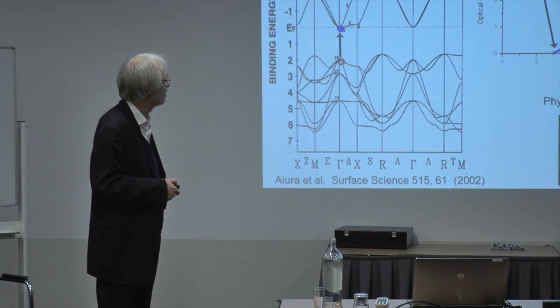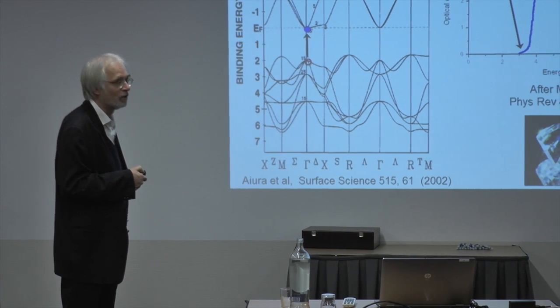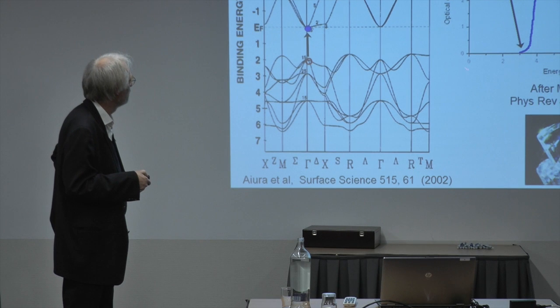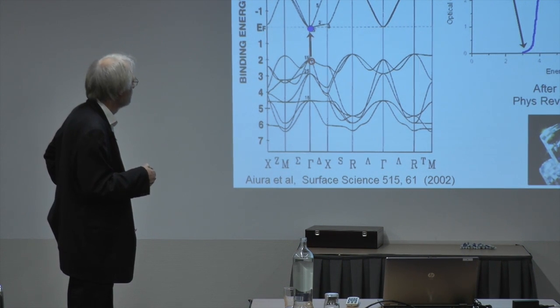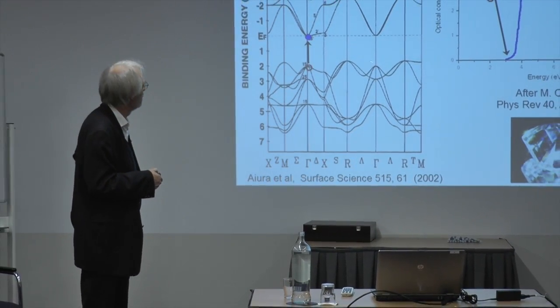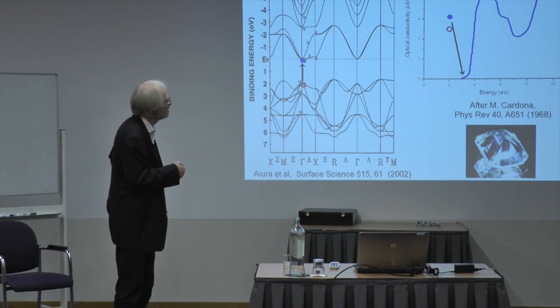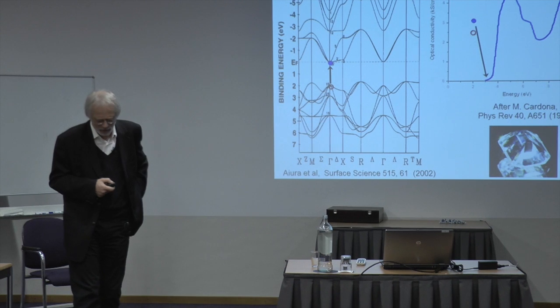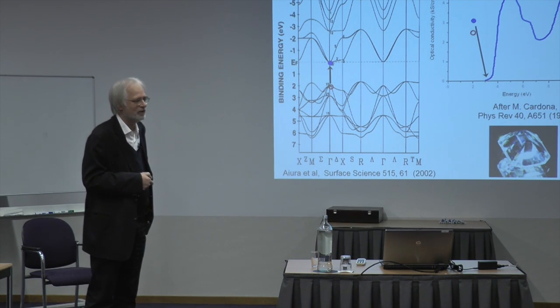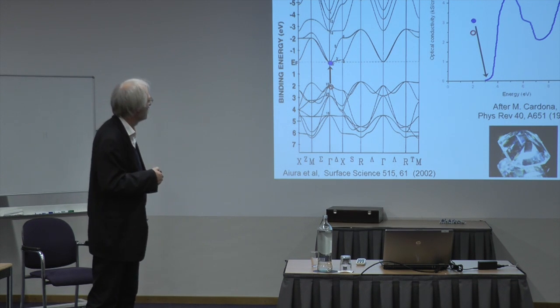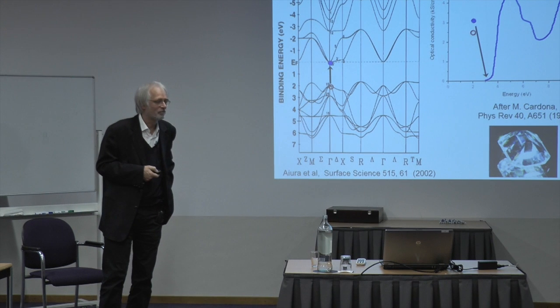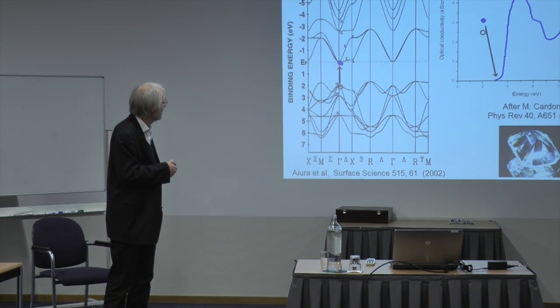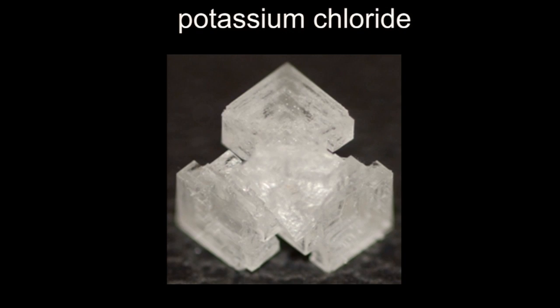The optical conductivity of strontium titanate was most properly measured already in 1968 by Manuel Cardona. It starts at around three electron volts — the actual gap — and goes up with all kinds of interband transitions. The first onset is precisely at that point, which is the first energy to create an electron-hole pair. For an insulator the Fermi energy is in the gap. So far nothing special, nothing to be excited about.